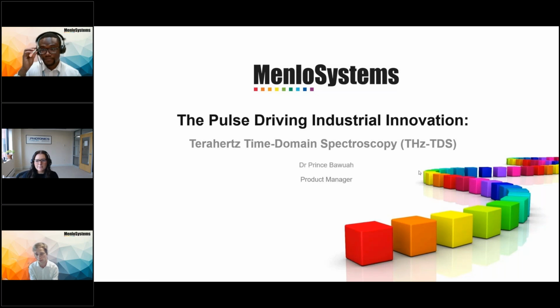Another very interesting one has been battery manufacturing, as they're being extruded, being able to measure in real time the conductivity, porosity, and thickness of the anode and cathode layers. And I was going to pick a third. A really interesting one we found has been looking at polymers as they are extruded and looking for defects and thicknesses and different material properties in those as they're being extruded out of a machine.